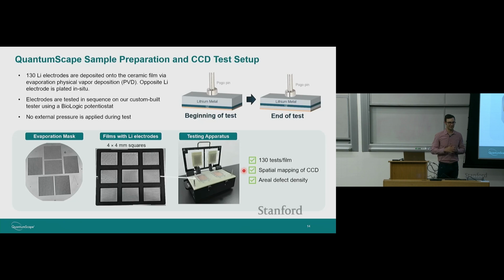So we deposit lithium via evaporation through this evaporation mask, and then we load onto a testing apparatus that has a lot of spring-loaded contacts that can come down and make contact with every electrode simultaneously, so that we can then, with software, sequence through all the devices and, like I said, measure about 1,000 data points in 16 hours. It also gives us some spatial mapping capability that we can then use for failure analysis and feedback. If we're seeing that one particular area failed early or a region of a material failed earlier than another region, we can then do some further analysis to figure out why. And that's been really important to closing the feedback loop and allowing us to improve further.